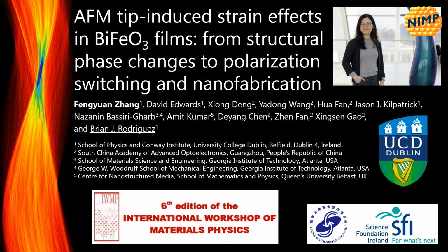I'm going to tell a story with two parts. Both parts have to do with scanning probe microscopy, which is what our group does. And we use conducting probes to do both conducting measurements as well as PFM. But we introduced something new for our group, which is using a very stiff single crystal diamond probe to carve out nanostructures in bismuth ferrite thin films.